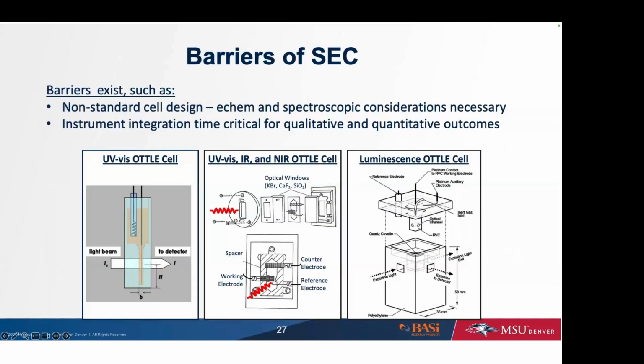All right, so some of the barriers that exist in these experiments are, because we have such versatility, while this is actually a boon to this field, it's also somewhat of a barrier because you have non-standard cell design. That makes it more complicated sometimes to make sure that you're getting the best setup for your application. You also need to make sure that your integration time between your instruments is appropriate to get qualitative and quantitative outcomes that are precisely measured for very fast processes. So basically, we are trying to make the integration time of the instrument faster than the process that's being measured. Of course, we want to be able to differentiate one signal from another, and we must be able to sync between the spectral and electrochemical instrumentation such that we can get real-time data.